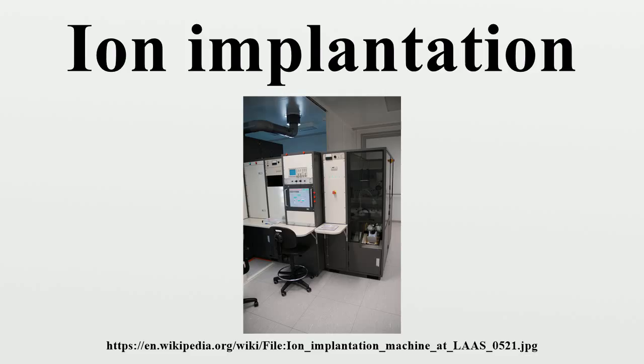Mesotaxy is the term for the growth of a crystallographically matching phase underneath the surface of the host crystal. In this process, ions are implanted at a high enough energy and dose into a material to create a layer of a second phase, and the temperature is controlled so that the crystal structure of the target is not destroyed. The crystal orientation of the layer can be engineered to match that of the target, even though the exact crystal structure and lattice constant may be very different. For example, after the implantation of nickel ions into a silicon wafer, a layer of nickel silicide can be grown in which the crystal orientation of the silicide matches that of the silicon.